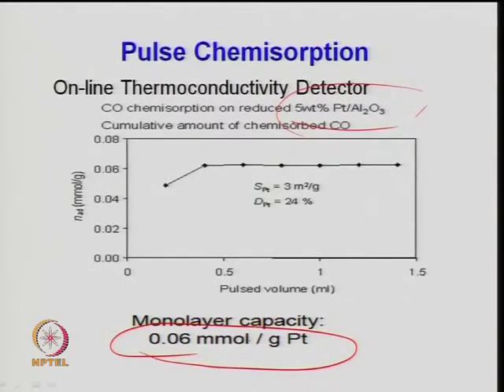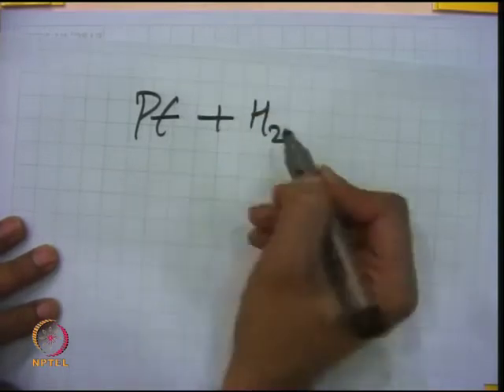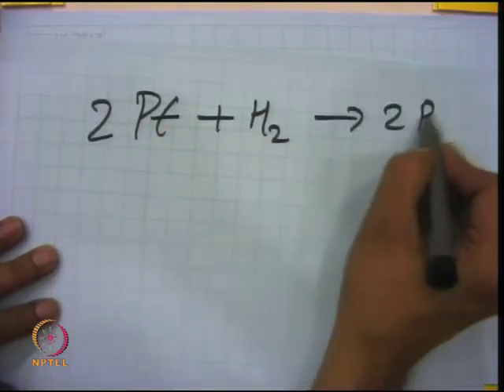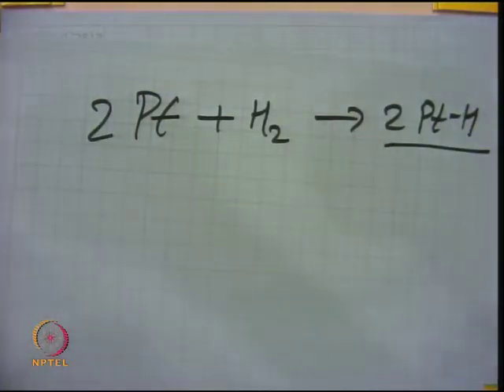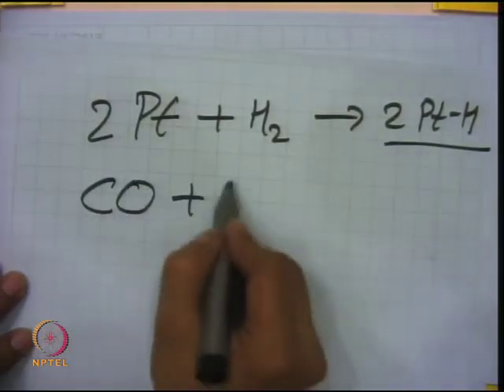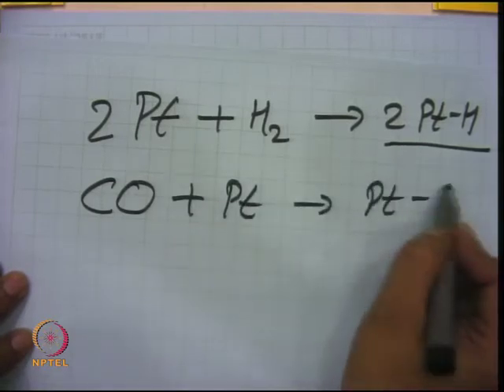V_m is the volume of carbon monoxide adsorbed on the active site, or the number of gram-moles of carbon monoxide adsorbed per gram of platinum. Platinum associatively adsorbs carbon monoxide, so you can determine the number of platinum atoms on which CO has been adsorbed. For hydrogen adsorption, we consider it dissociative, so stoichiometry should be known a priori. When platinum reacts with hydrogen dissociatively, 2Pt reacts to give 2Pt-H, a chemical reaction taking place here.